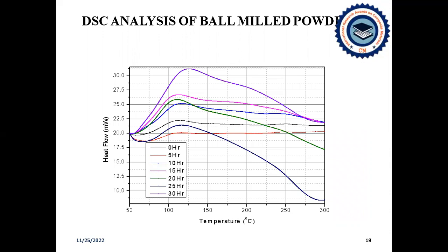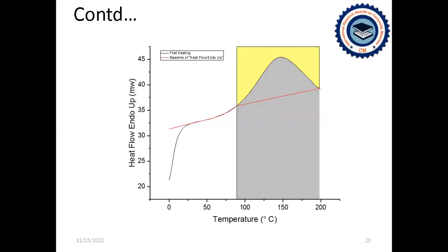When it comes to the DSC analysis of the ball milled powder, it can be observed that the heat flow is around a temperature of 110 to 120 degrees Celsius, where the phase transition from the crystalline to amorphous structure has taken place at the temperature range of 100 to 150 degrees Celsius, which suggests the formation of new phases due to the ball milling process.